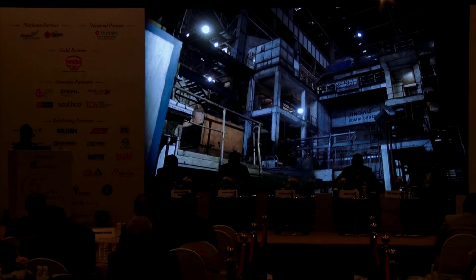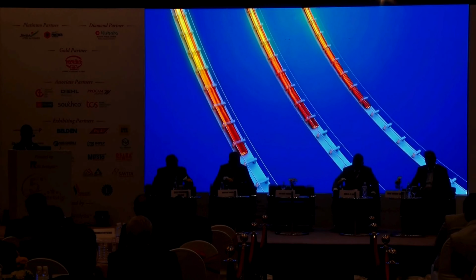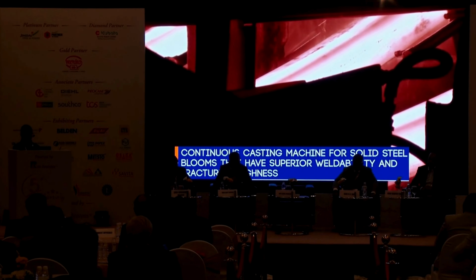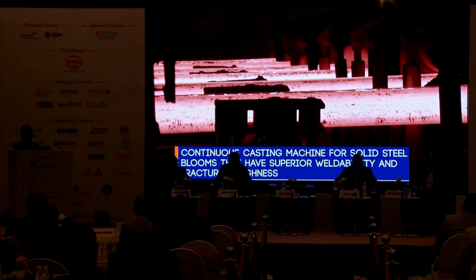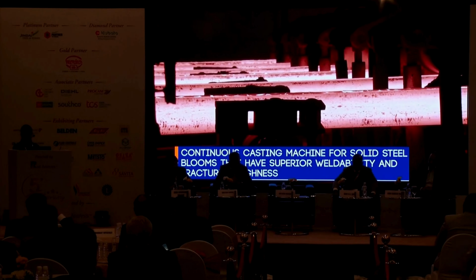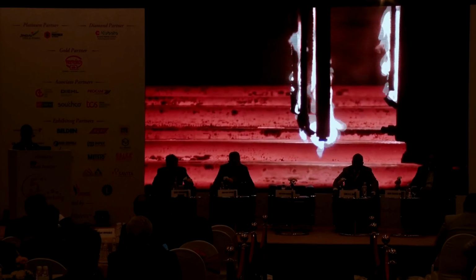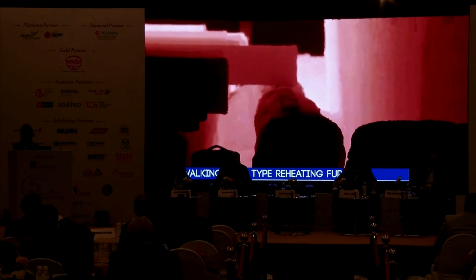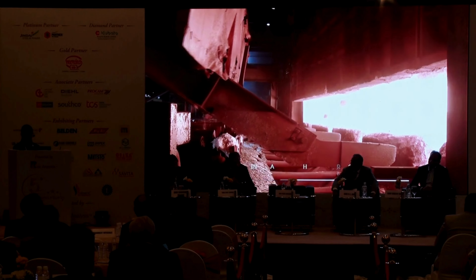The clean liquid steel is then cast into solid steel blooms using the continuous casting machine CCM, equipped with electromagnetic stirring EMS, ensuring excellent cleanliness, soundness, reduced inclusions and higher equiaxed zone, resulting in superior quality of casting. These steel blooms are then reheated in a walking beam type of furnace prior to rolling to ensure uniform heating, prevention of skid marks across the blooms.